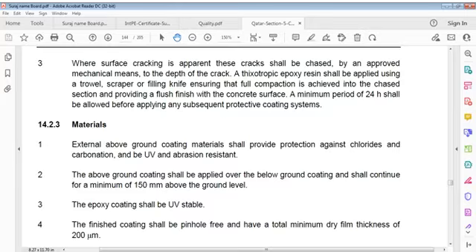Where surface cracking is apparent, these cracks shall be chased by an approved mechanical means to depth of crack. A thixotropic epoxy resin shall be applied using a trowel, scraper or filling knife, ensuring that full compaction is achieved into chased section and providing a flush finish with concrete surface. Minimum period of 24 hours shall be allowed before applying any subsequent protective coating system.